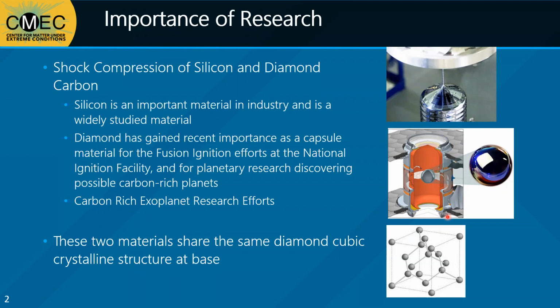which resulted in their net energy output from the fusion reaction. In their experiments, diamond carbon was one of the key materials as it was used for the fuel capsule, which holds and compresses the deuterium and tritium inside. Diamond also has its place in planetary research. The pressures and temperatures present on Neptune and Uranus make it possible for carbon to vaporize and rise through the layers of the atmosphere, then condense into diamond chains and rain back down in a type of carbon cycle.